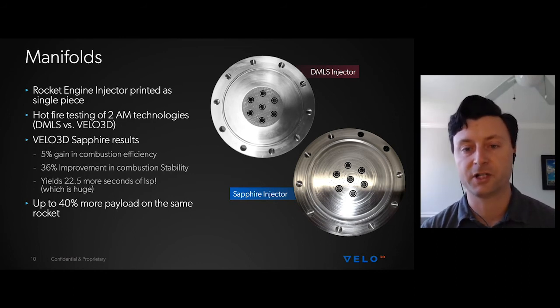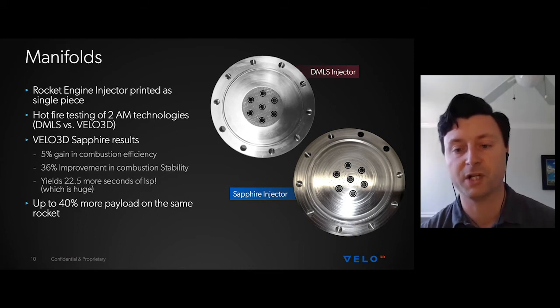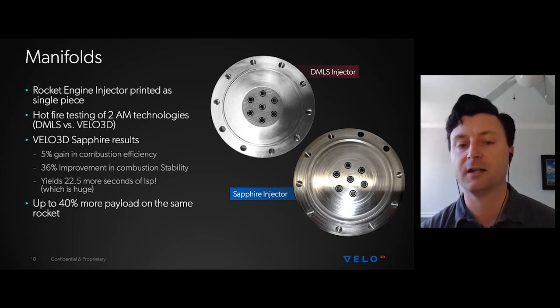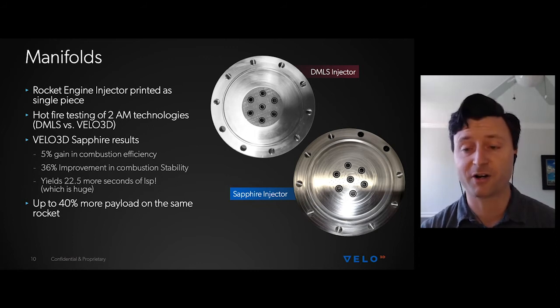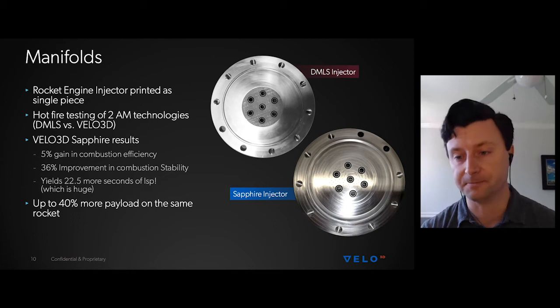Interstellar printed one on a traditional DMLS system and then printed one on the Velo 3D Sapphire system. And they found some pretty remarkable improvements from printing it on the Sapphire system. So they had a 5% gain in combustion efficiency, which, if you're not really familiar with rocket engines, doesn't sound like a lot. But 5% is a really remarkable amount of combustion efficiency gain, considering that it's the exact same part. There were no design changes between these two. So this extra 22.5 seconds of specific impulse is really pretty phenomenal and something that they were very surprised to see at the end of the day.